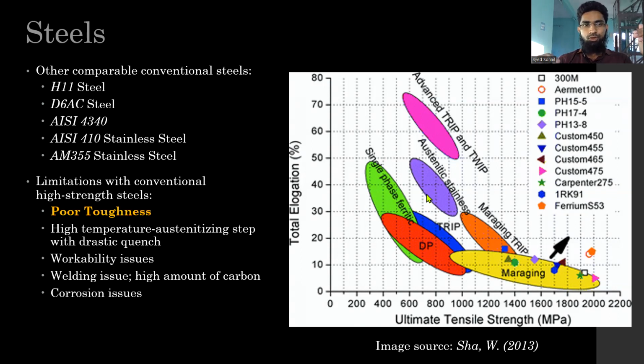As I mentioned here, there are limitations with conventional high strength steels. The first thing to note is poor toughness, which I highlight. They have poor toughness and require a high temperature austenizing step and a drastic quench. These steels require a quench process. Once they are formed, bringing them to room temperature requires a quench. Whereas with maraging steel, we don't require the drastic quench. We can do air quenching. Air cooling is preferable and has been proved satisfactory to achieve the strength and all those other requirements from the application perspective.